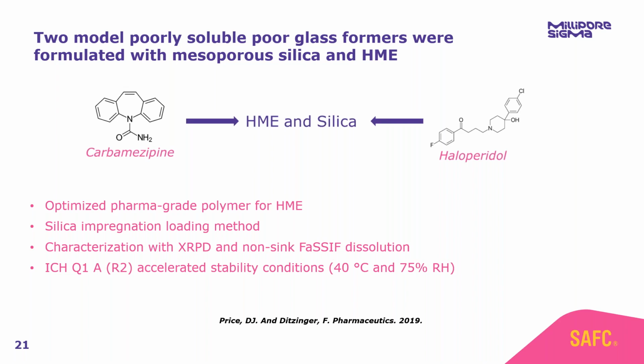We went through an entire optimization process for hot melt extrusion. We didn't just pick any old polymer off the shelf. We combined experimental with computational prediction to make sure that we had the most optimal polymer. We then loaded these molecules onto mesoporous silica, and then we characterized the formulations with XRPD and with non-sink FaSSIF dissolution. We then stored these formulations under ICH Q1A accelerated stability conditions of 40 degrees Celsius and 75% relative humidity. Then we assessed any changes in these parameters over the course of a 3-month stability study.